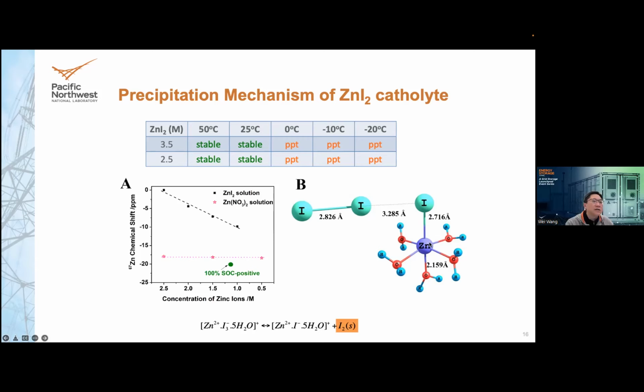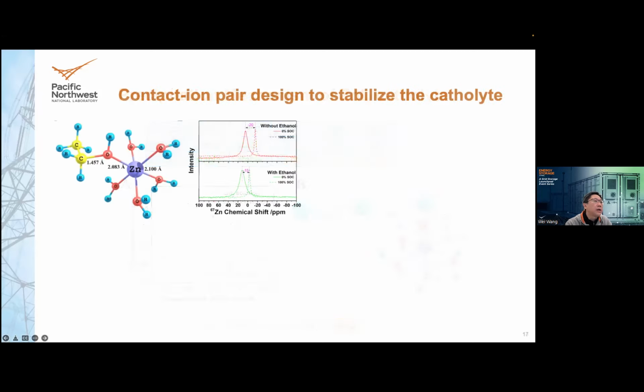In this case it is the zinc. When the zinc gets close to the triiodide, it will actually strip one iodide away and leave the iodine to precipitate out. And this is, I believe, an exothermic reaction, so it happens more at lower temperature. Once we understand this, we can design another contact ion pair to prevent this electron sharing.